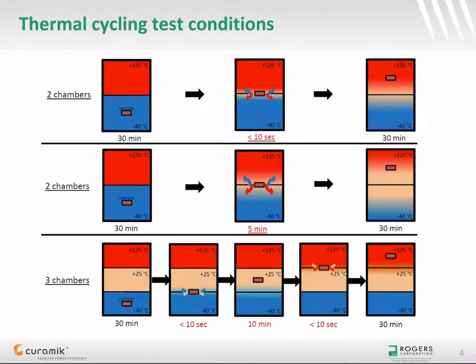Thermal cycling is the most common test method used for assessment of the reliability of metallized ceramic substrates. It is an accelerated test method and as such cannot give any information about the lifetime of the substrates in a real application case, but provides a good comparison between various substrates.